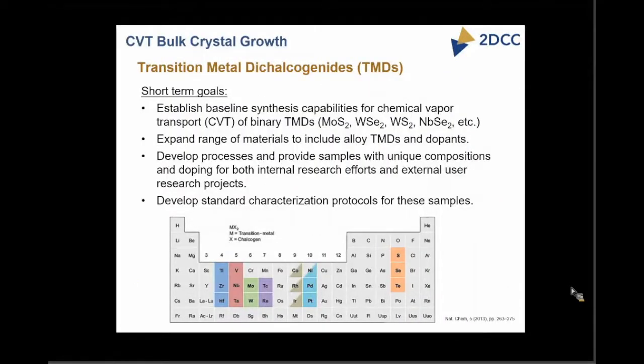So, in terms of where we're at with the materials, the initial focus on transition metal dichalcogenides has been structured to, first of all, establish a baseline synthesis capability for CVT transported binary TMDs. And the materials shown there would be the first ones on the list that we'll be synthesizing as this material comes online. And we hope to rapidly expand the range of materials to look at alloys and dopants of these materials. Again, the focus here is to look at samples with unique compositions, unique doping for both internal and external research.